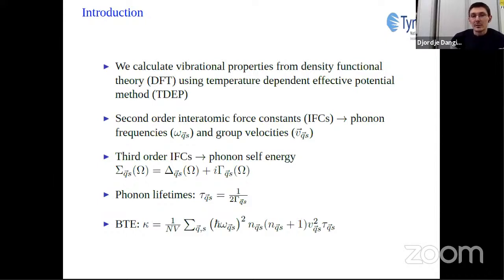How do we use Boltzmann transport equation in practice? Well, we first calculate vibrational properties of the materials from the density functional theory, and then using, for example, the temperature-dependent effective potential method, as we did in our case. Of course, this method, Boltzmann transport equation, and also the method that I'm going to show later on, are not only viable with using this method of extracting vibrational properties. You could practically use whatever you want. So what we do is we expand the material Hamiltonian in the Taylor series with respect to the atomic displacement. The coefficients in this expansion are called interatomic force constants.